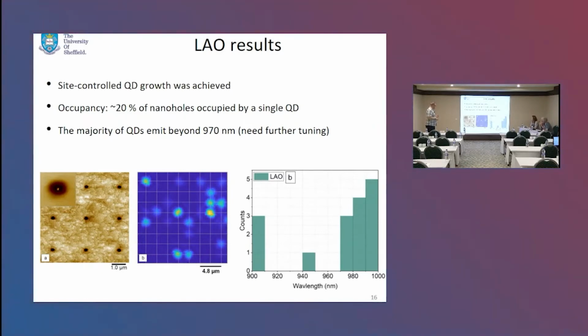So again, in AFM, we can see a dot sitting at the bottom. The LAO pits are quite sort of scooped and quite large because of the process. We only got to about 20% occupancy when we look in the PL map, but they are in the positions that we can draw the lines that are guides to the eye. But a lot of the dots are emitting beyond 970, so we'll need to pull those back in order to use them with silicon detectors.